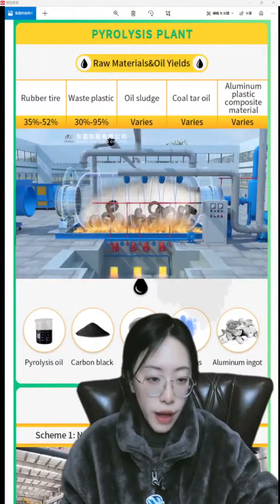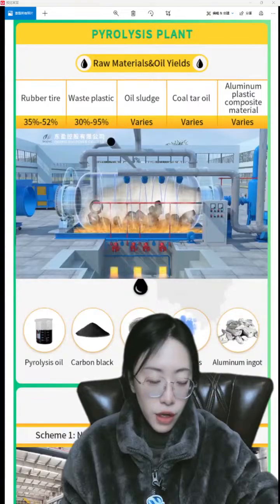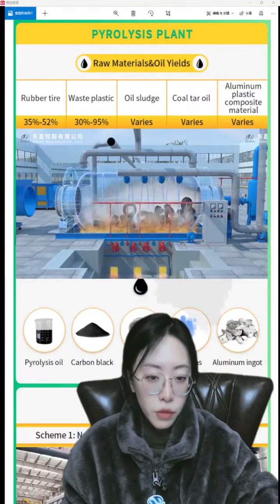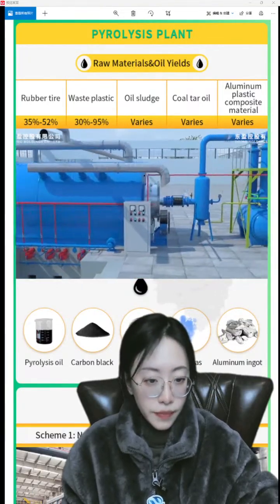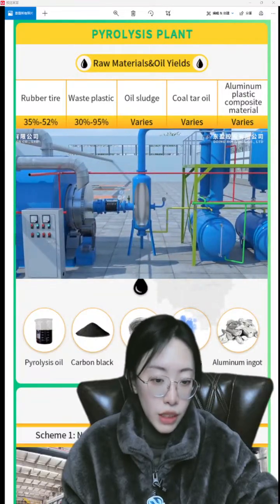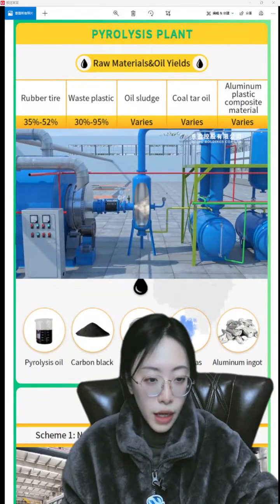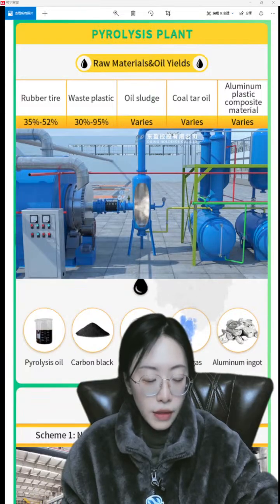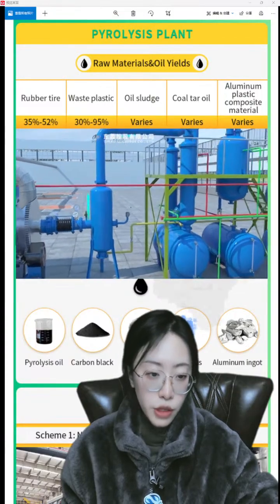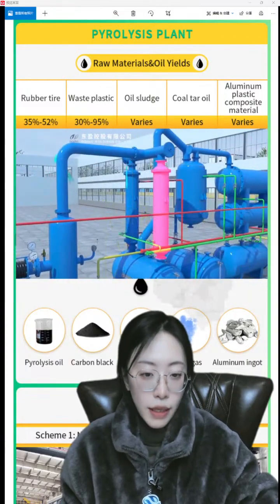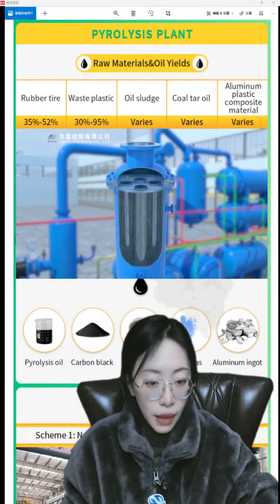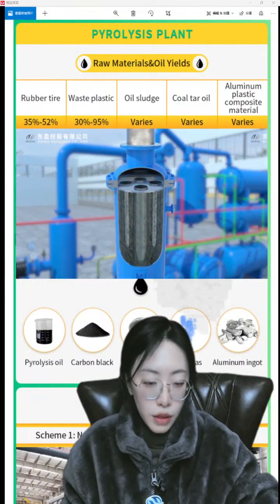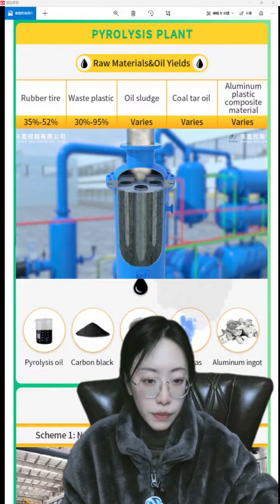After heating for about 2 hours, the temperature will gradually rise and oil will be generated, at nearly 120 to 160 degrees. The white gas is a mixed gas of the oil gas and tail gas. They will come out to the outlet and go to the buffer tank, which can slow down the gas, make it stay in the cooling system for more time, and deposit the impurities.